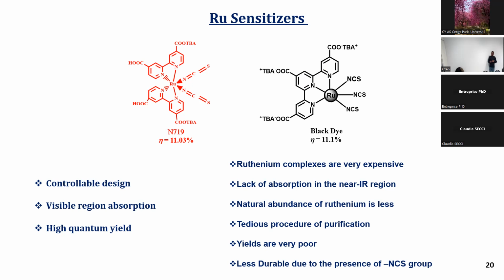In this, ruthenium complexes are used. This is very expensive, and ruthenium complexes' absorption is not in the near IR region, so absorption is very low, only up to the UV-visible region. The natural amount of ruthenium is very small, and the synthesis is not easy. It is a tedious synthesis. Stability is poor. So to overcome these issues, they replaced the ruthenium sensitizers.